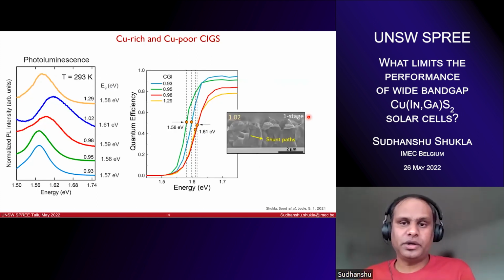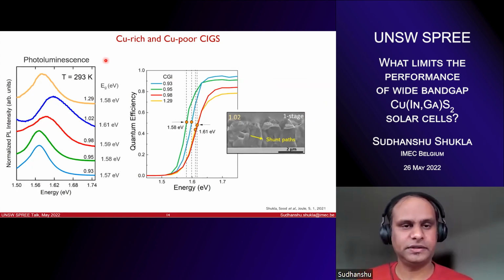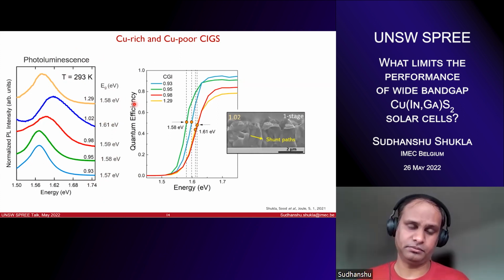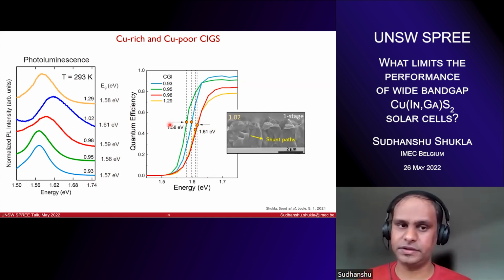We then move on to quantify the band gap of these absorbers. So we did room temperature photoluminescence. And what you could see, we have absorbers all the way from copper rich to copper poor, and they have a band gap in the range 1.57 to 1.61 maximum. So we not only check the band gap from photoluminescence, we also measure the quantum efficiency of the full device. Looking at these inflection points, they are consistent with the band gaps that we have obtained from photoluminescence.